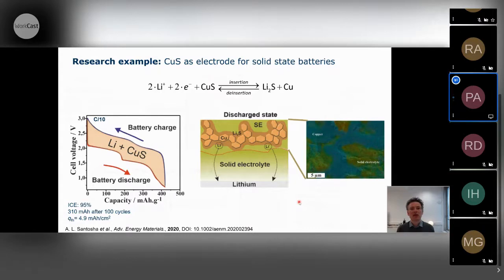So this can be all kinds of binary, let's say, oxides or sulfides, and we're trying to use them in solid-state batteries. Very often you think this is a bad idea because these so-called conversion reactions suffer from a large volume expansion during cycling. But I want to show you on this slide that actually quite decent behavior is possible for some of these compounds. And copper sulfide is really a special material that surprisingly works well in a solid-state